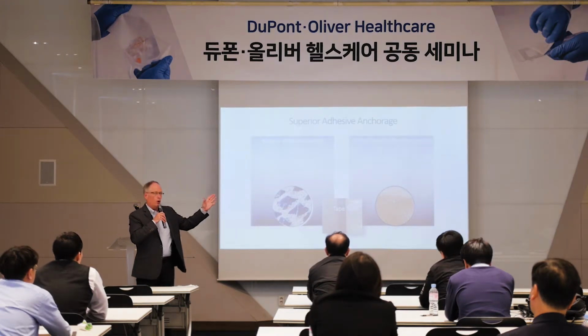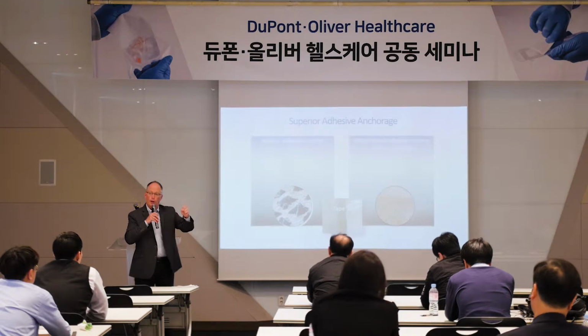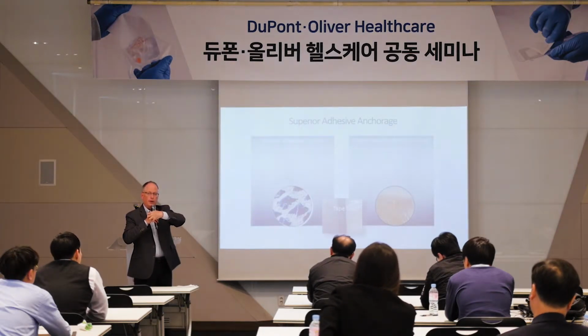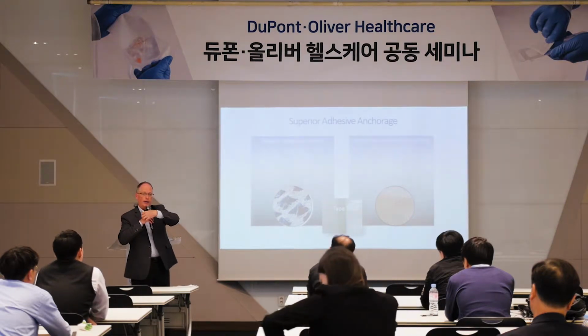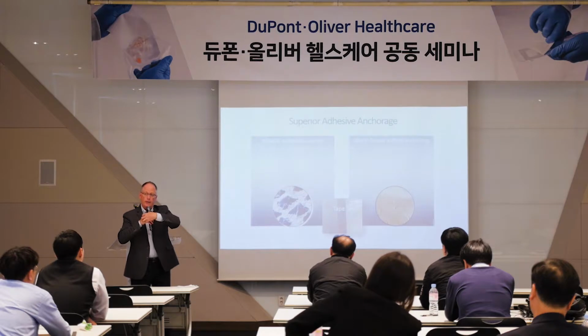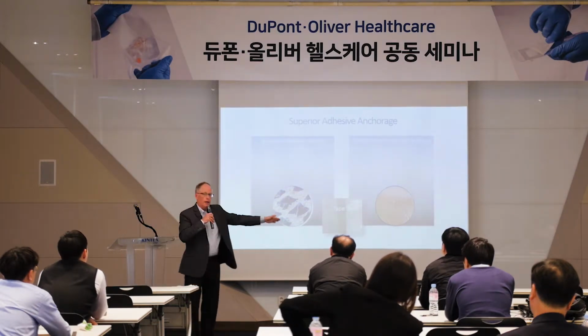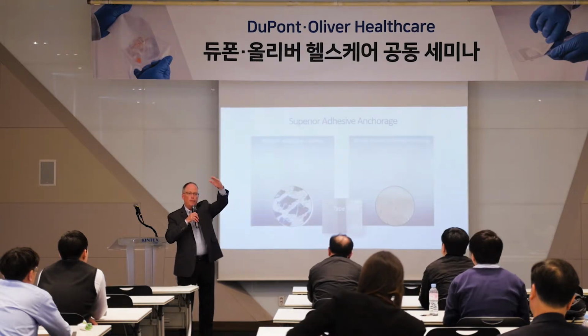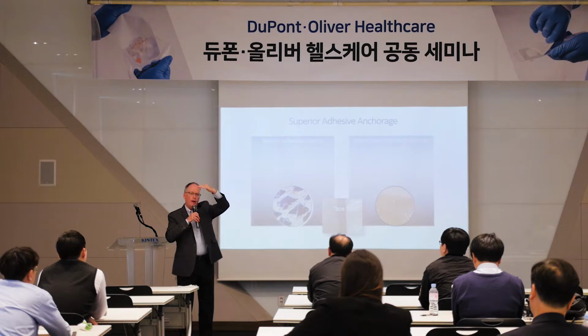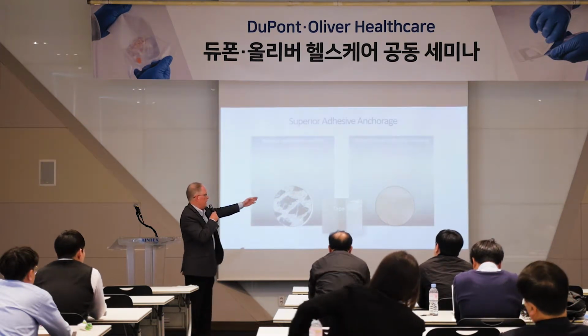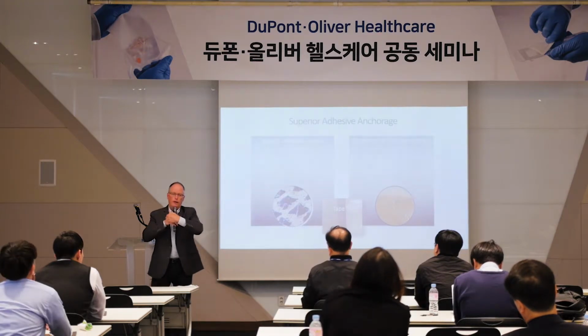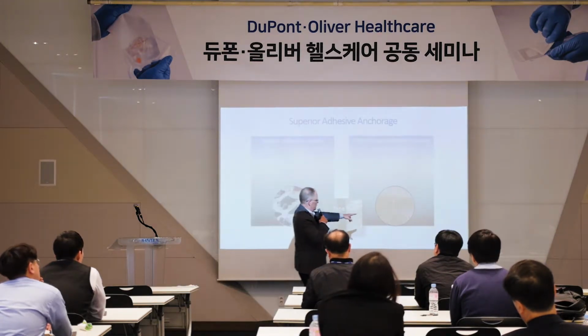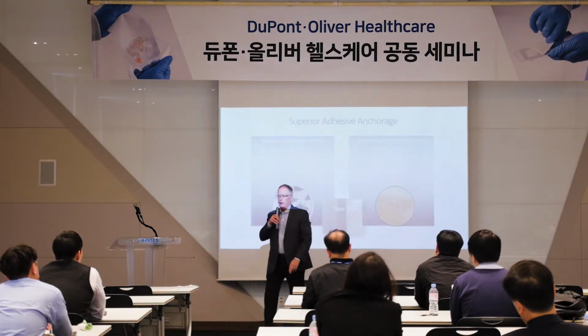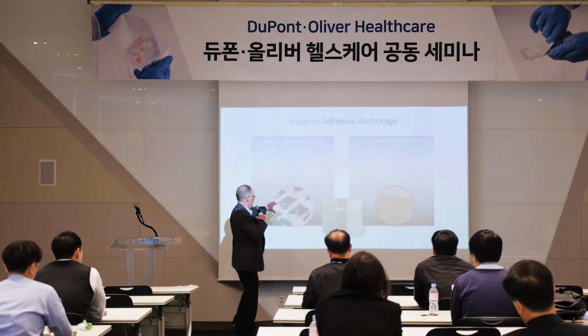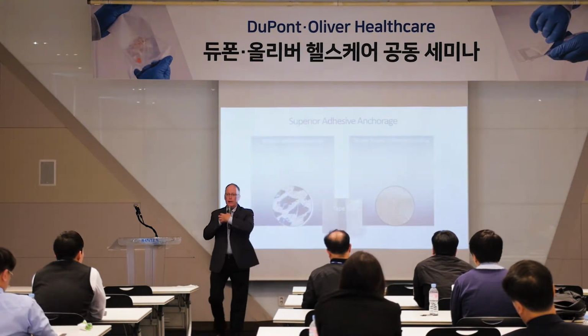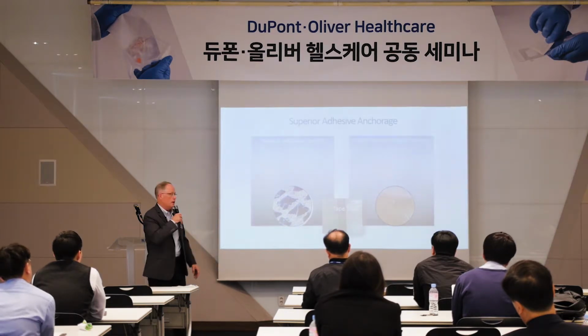We just saw that video, and if you think about the dots of adhesive in hot melt, they're molten, at high temperature. When they hit the Tyvek, they're hit with an impression cylinder and driven into the Tyvek, and because they're molten, they grab the Tyvek fibers and anchor very well. With water-based, you saw it's a flood coating on the surface, and then it goes into an oven to dry it. It's kind of sitting on the surface of the Tyvek. It has pretty good anchorage, but if you've got a device that's going to rub against the lid stock, you can get some particulate generation, so you have to be careful about that. Whereas with hot melt, because of the molten adhesive, it really anchors well to the Tyvek and is less likely to rub off and particulate.